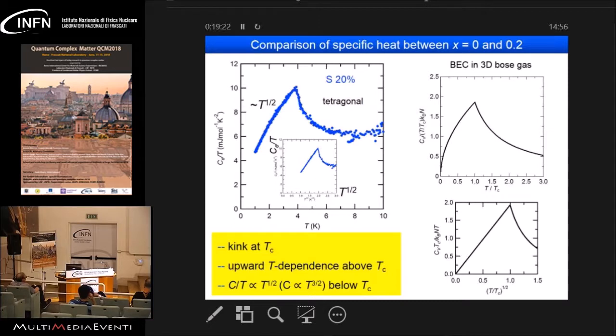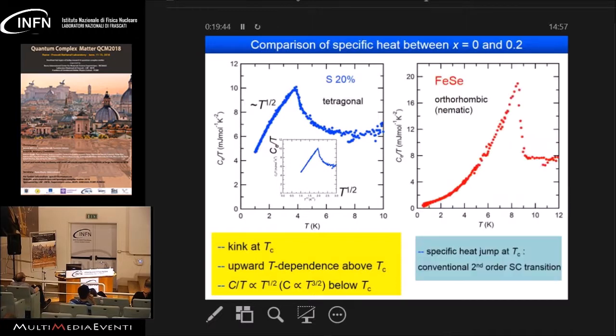So this kind of feature is surprisingly similar to what is expected in the BEC case, and actually the simplest 3D Bose gas case. So as you can see, you have a gradual increase, and you have a square root T dependence just below Tc. Okay. So here's again the comparison. So this is the iron selenide, which is in the nematic phase, and here is the 20% sulfur doping, which is in the tetragonal phase. You see the quite difference.